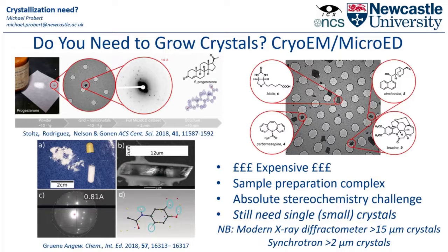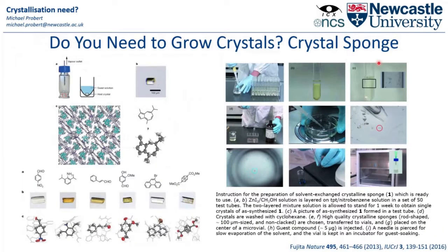But what about if we don't need to grow crystals at all? If we just want to analyze our compound, we could use the crystal sponge technique, sort of pioneered by Fujita, where you soak your analyte into a host crystal, and you use the cage-like structure to trap your compound in hopefully ordered orientations within the structure, and then when you analyze the host structure, you gain analysis of your compound as well. This has been used very successfully across a range of compounds where molecular information is gathered. The problem with this technique is that it doesn't give you data on the intermolecular interactions, the full crystal structure of your compound, because the compound is there as a guest within the host.